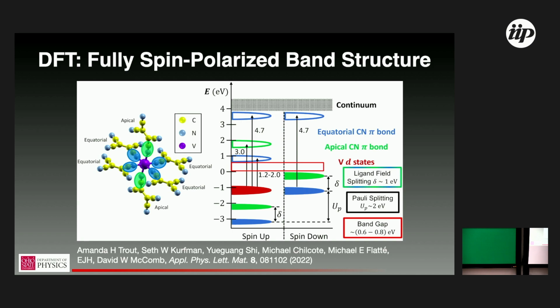And then this red box is defining the band gap, which is indirect in spin space. So this is a fully spin polarized organic semiconductor, if you want to think of it that way, or a half semiconductor if you want to borrow from the half metal community. So this is a pretty remarkable density of states. There's just not many materials that look like this, and I think that this is part of the reason why we're able to see the properties that we observe. So let me pause here because I'm about to dive into the data, but this is sort of just starting with an orientation for the crystal structure.